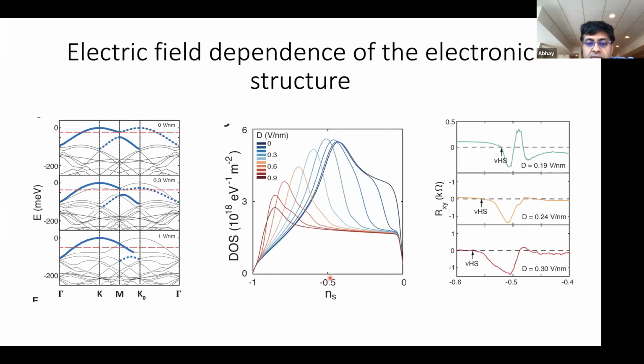Okay. So in twisted WSe2, here's how we believe the argument goes. If you look at the band structure in the absence of this electric field, it features a Van Hove singularity, and this Van Hove singularity is on one side of the half filling point. As you start to apply this electric field, the Van Hove singularity moves through half filling, and eventually, for a very large electric field, it goes very far away from half filling. The insulating state we observe in experiment is mostly in the region where the Van Hove singularity is going through half filling. Our explanation is that correlations are moderate, and you need the density of states to be high in order to realize the insulating state. Does that make sense?